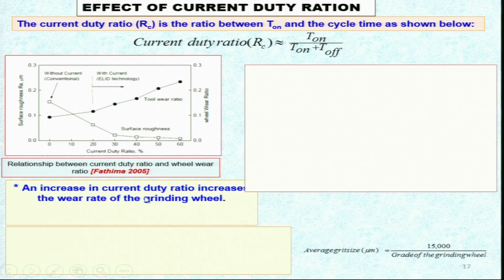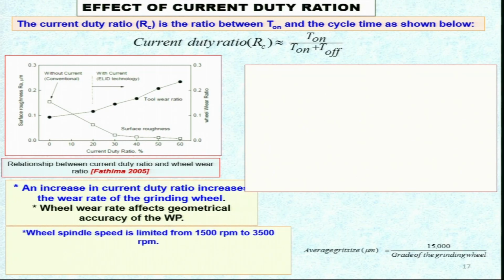An increase in current duty ratio increases the wear rate of the grinding wheel, as we can see here, and then the wheel wear rate affects the geometrical accuracy of the workpiece. This is very important, because if wheel wear is fast, then it will affect the geometrical accuracy and tolerances of the workpiece which is being finished.